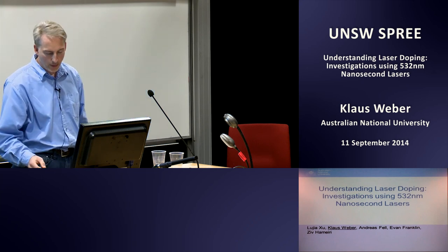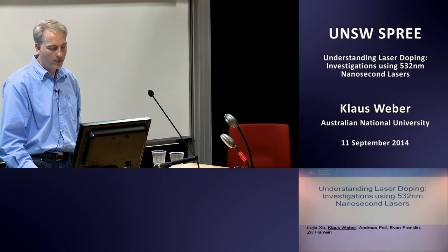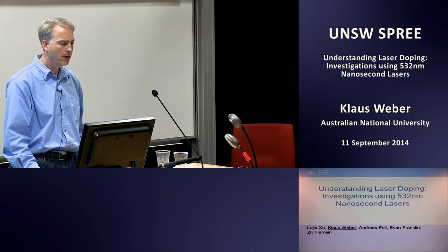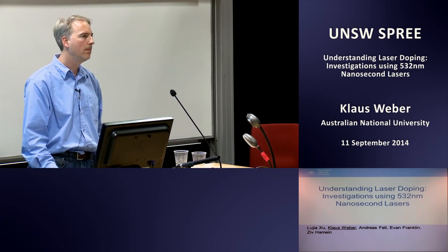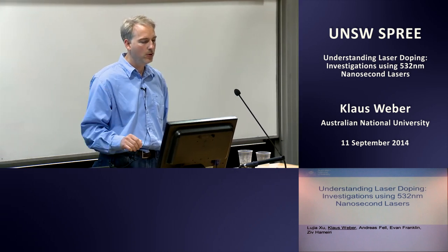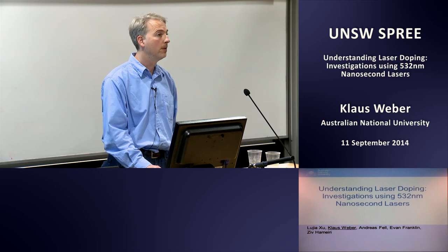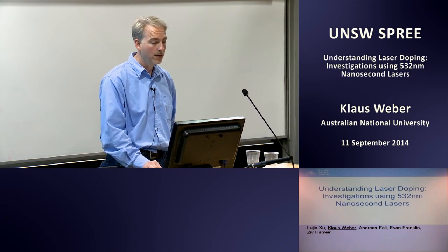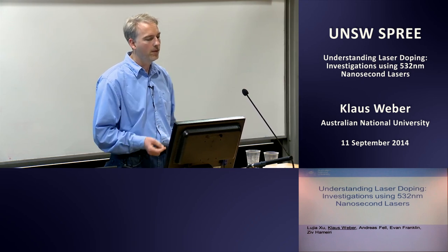Okay, so one thing I didn't mention is that the diffusions that we used were around 70 ohms per square in that region. And we just used a boron diffusion tube, a temperature diffusion tube, for that. So I don't have the actual profiles here.